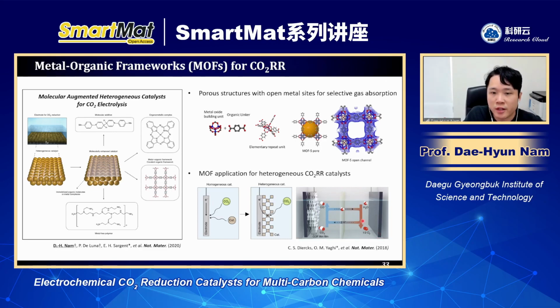These days, molecular-augmented strategies have received great attention to enhance the selectivity and the energy efficiency. It means combining a heterogeneous metallic surface with molecular add-layers. And MOFs, metal organic frameworks, can also be used in this strategy for heterogeneous CO2 reduction catalysts. As you can see, a MOF has a very finely controlled porous structure, and this is very good for gas capture. It means it can enhance the local CO2 concentration.